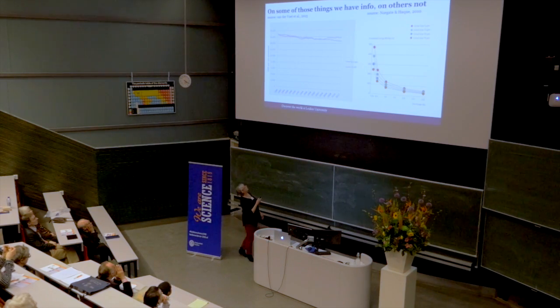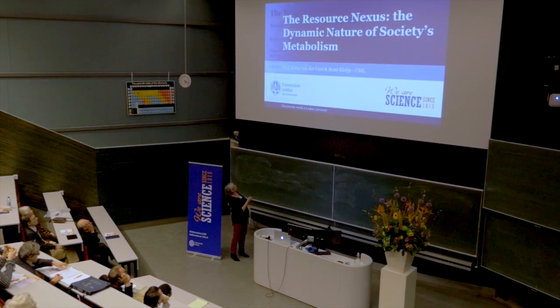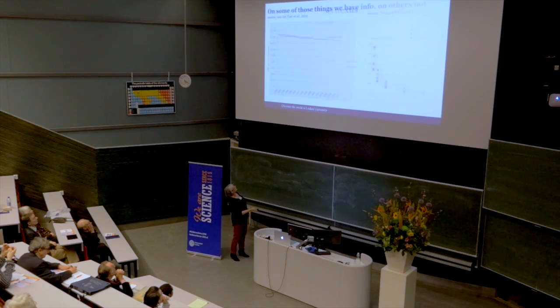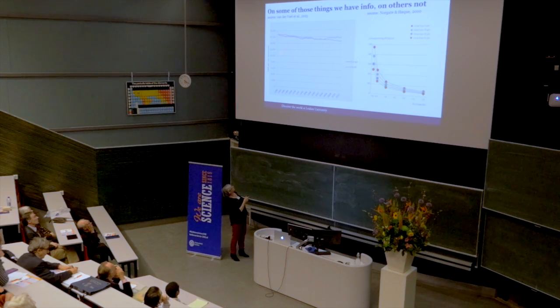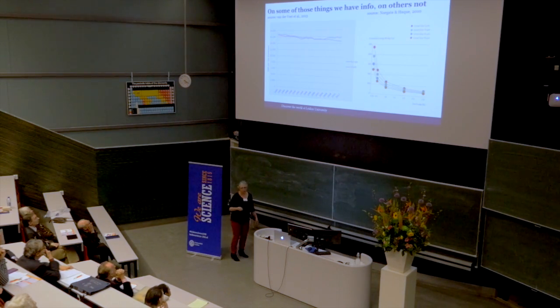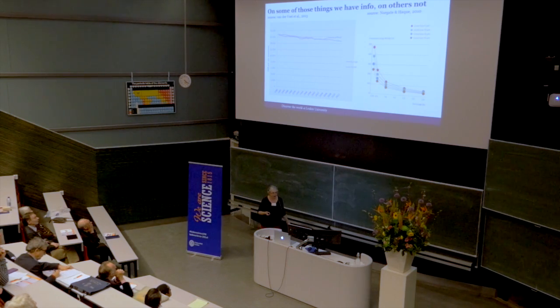On the left-hand side here, you see the development of the amount of electricity in kilowatt hour per ton that is used to produce aluminium. Starting point is 1980, end point is about now. We have Europe and we have the world. And what you can see from this is that it hasn't changed a lot. The efficiency has improved just a little bit, but not a lot.